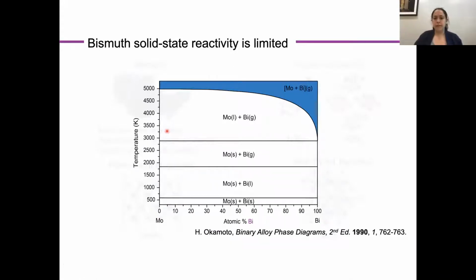And I think this is best encapsulated by this phase diagram here, which is from the literature for molybdenum and bismuth, which is going to be the focus for the rest of this talk. And you can see that these elements stay immiscible in this two-phase region up to thousands of degrees Kelvin, when they both enter the gaseous state. And in fact, this is representative of group 6 element chemistry more generally with bismuth. And by that, I include chromium and tungsten as well.